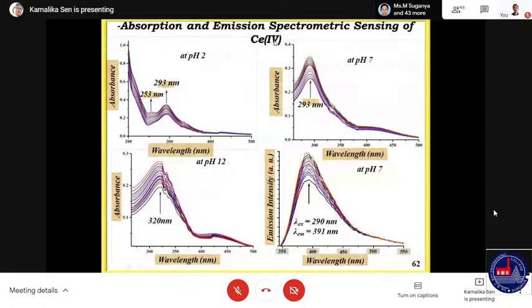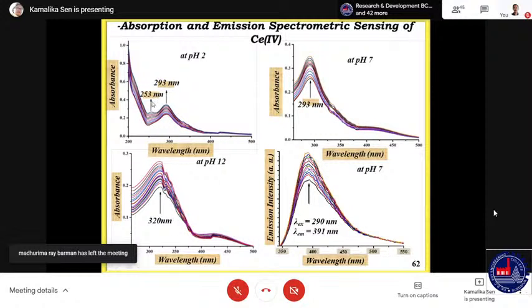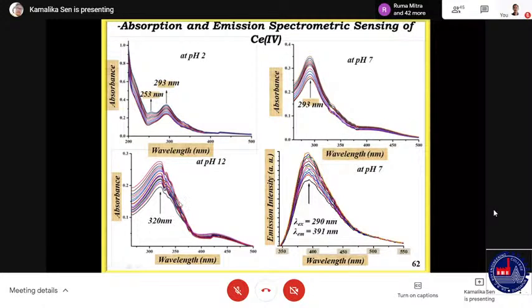See, for cerium 4 spectral sensing, we have seen 4 conditions. For absorption spectra, at pH 2, pH 7, and pH 12, we can see different peaks which increase with increasing concentration of cerium. That means with increasing concentration of cerium, the absorption spectra show increasing peaks at 253 and 293 nanometer at pH 2, at pH 7 at 293 nanometer, and at pH 12 at 320 nanometer. If we see the fluorescence spectrum and excite it at 290 nanometer, we can see an emission at 391 nanometer at pH 7. It also shows a turn on fluorescence in presence of cerium 4.